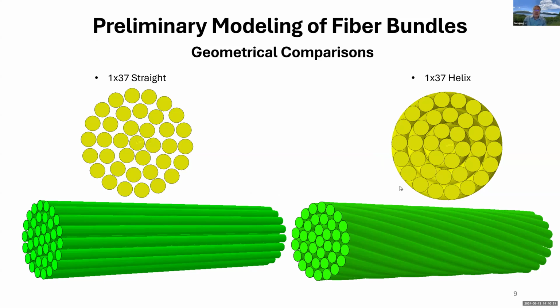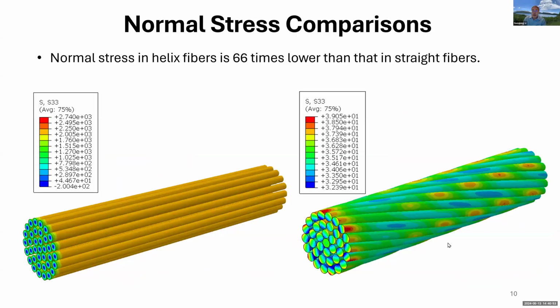If you just use straight fibers, of course, you have no way to change it because it's a material property, right? So we're trying to see if we change the configuration of the fibers. Here you see that we have two bundles. One is a straight fiber bundle, another is a helical configuration. We did finite element modeling and compared them. Here is the normal stress comparison. You can see the normal stress in the helical fiber is 66 times lower than in the straight fibers. Definitely this is a good sign, right?